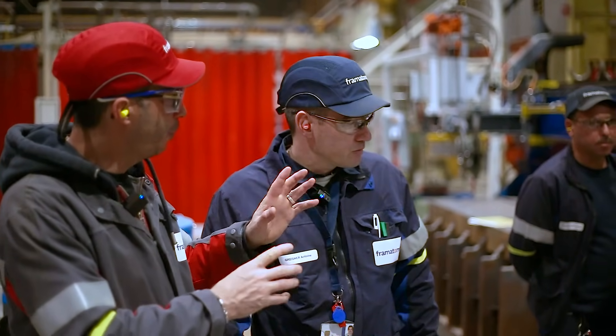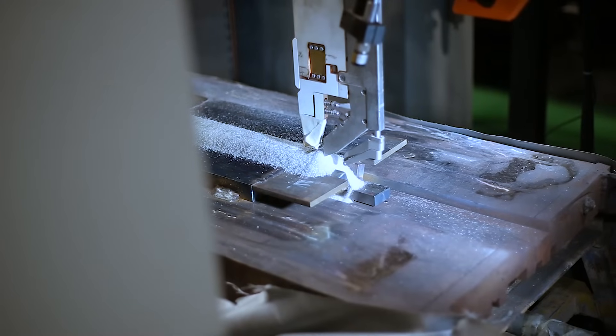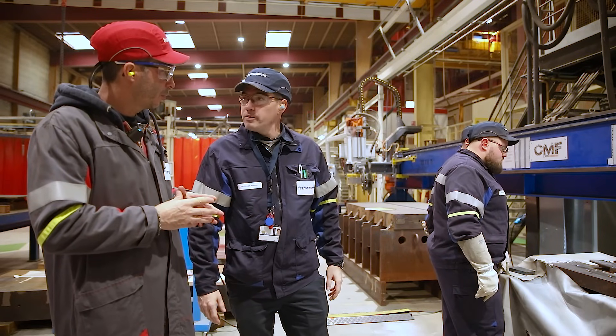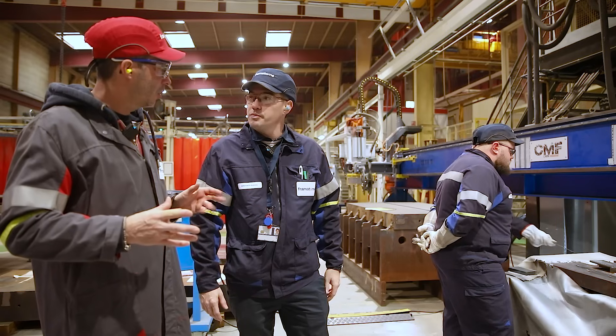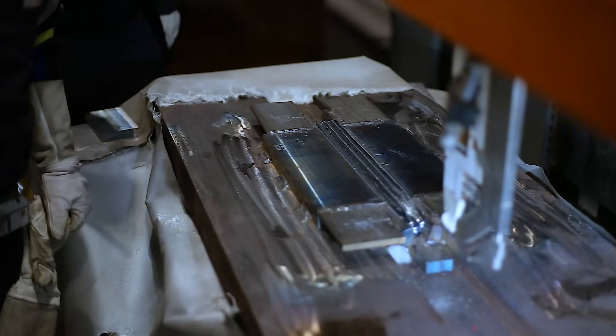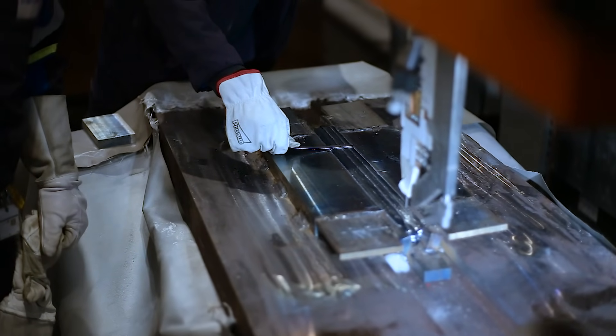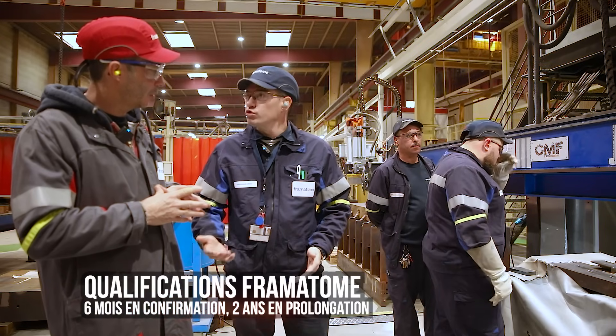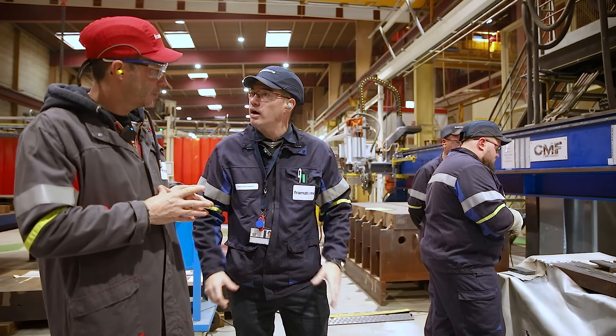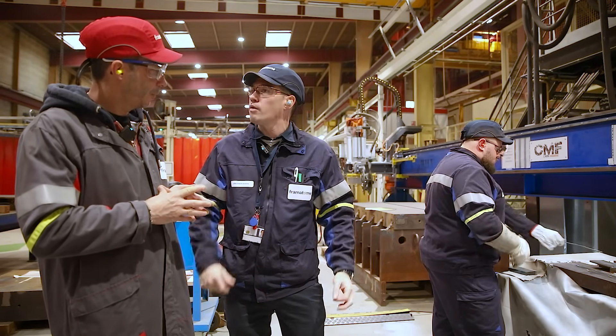The flux partially transforms into slag. The material here is low-alloy steel. Weld length is approximately 350 mm — the standard length for welding qualifications. Once complete, 100% volumetric radiographic inspection is performed. A qualification is valid for 6 months with confirmation and 2 years in production at Framatome, renewed every 6 months for confirmation and every 2 years in production.